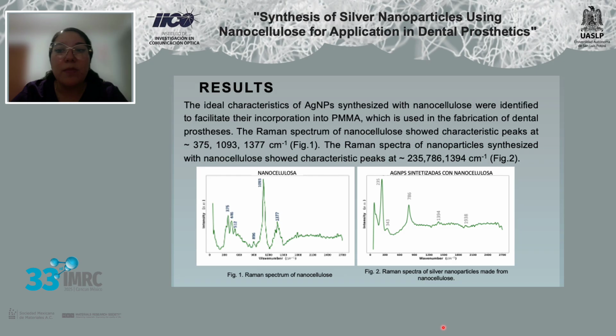As results, the Raman spectrum of nanocellulose showed characteristic peaks, which are associated with characteristic vibrations of the polymeric matrix and its interactions with the nanoparticles, confirming their correct formation. And the important peaks are this 375, the next 1093, and the other one 1375. And we have the nanoparticles synthesized in the presence of nanocellulose, which present peaks at 235, 786, and 1394.